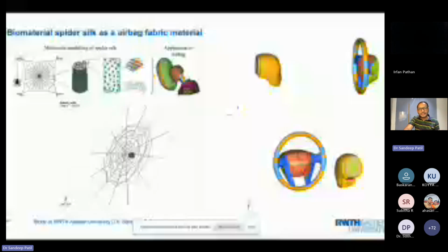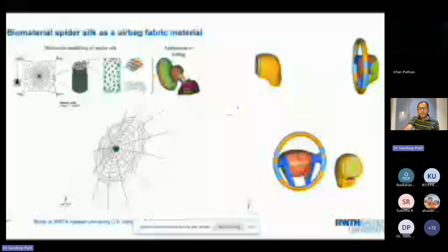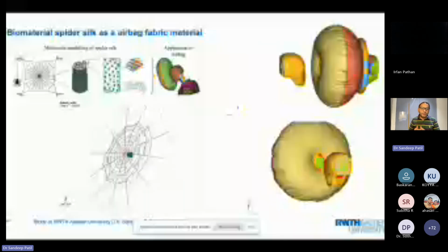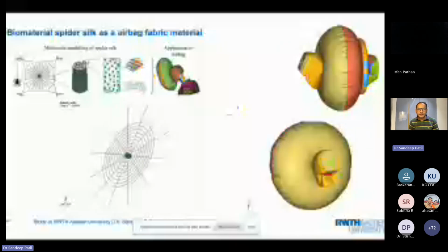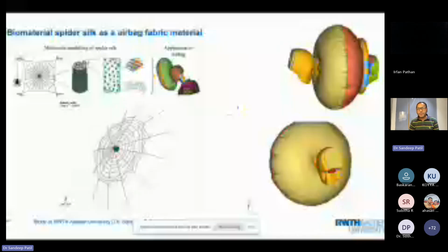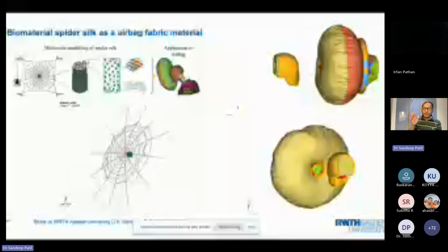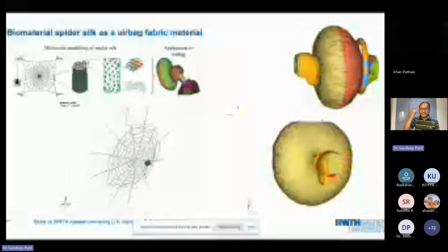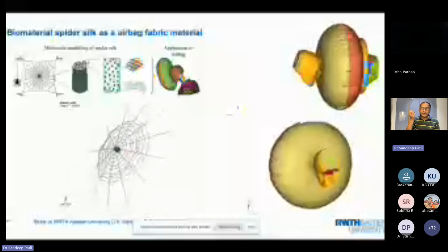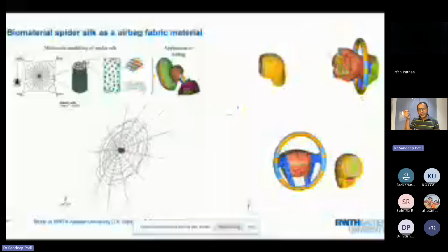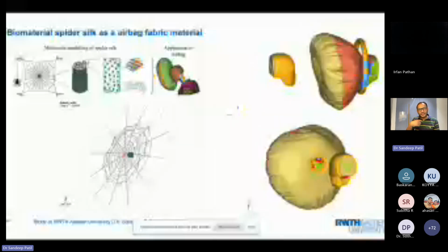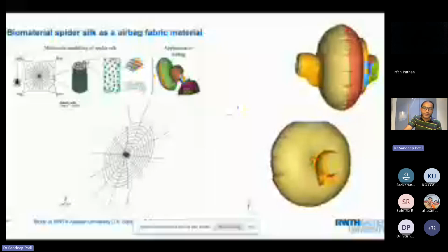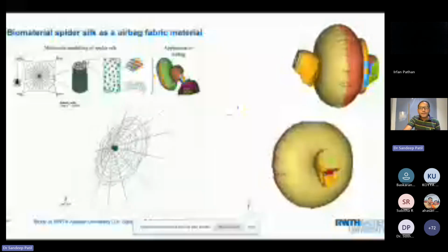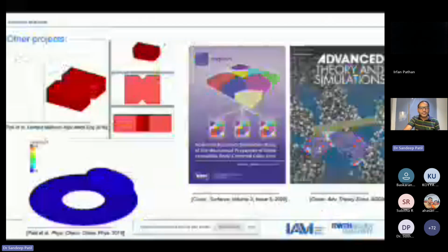the biomaterial spider silk as an airbag fabric material, which can be a potential one. So if you look here, the simple thing is that with airbags right now, people are using nylon 66, which is a highly elastic material. But if you have some dissipation in it, you can get a lower HIC. The lower the HIC, which is the head injury criteria index, the better. So we found that spider silk is a better airbag material, and we have been carrying out some experiments at our textile institute.